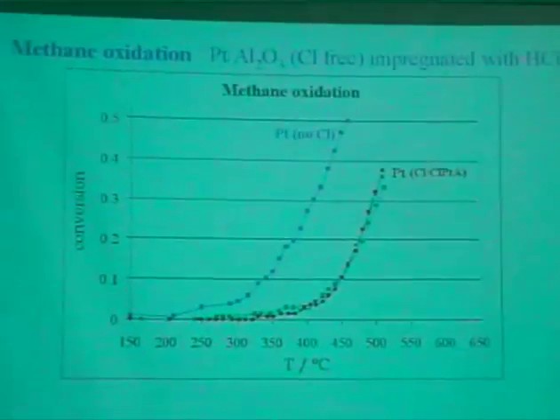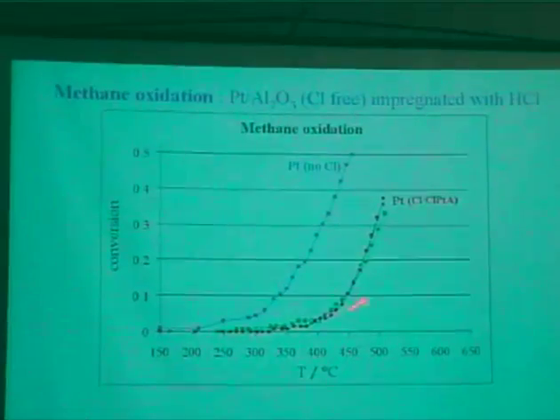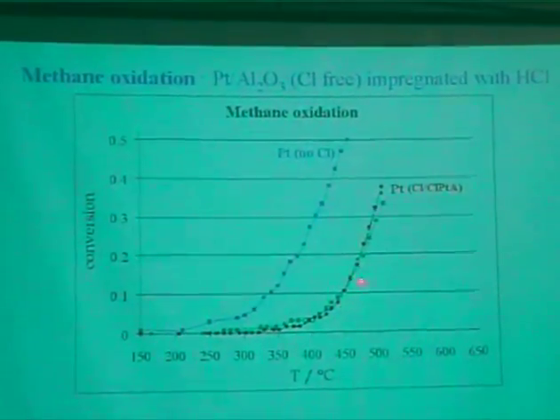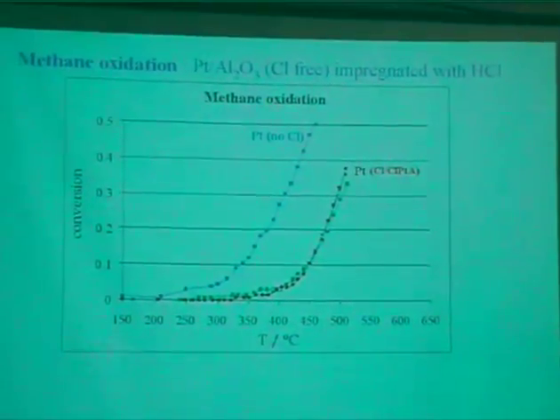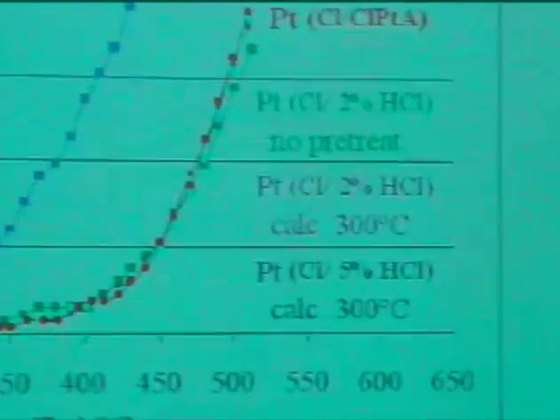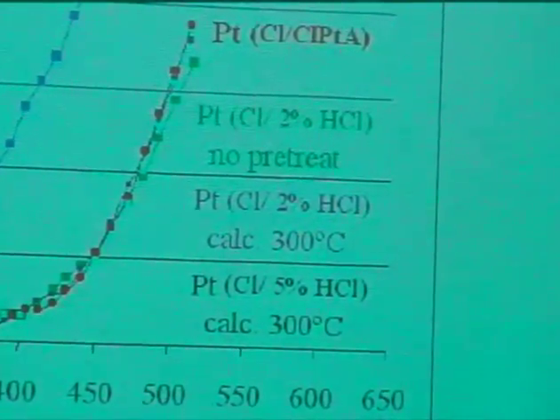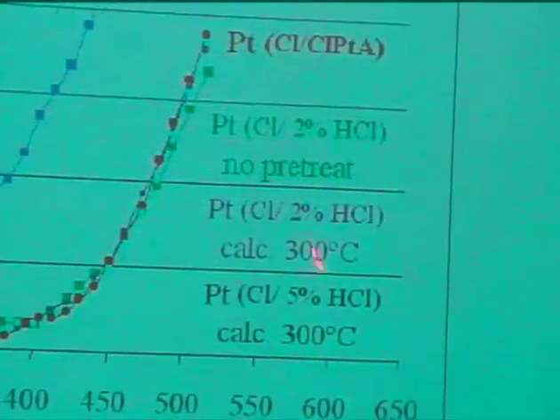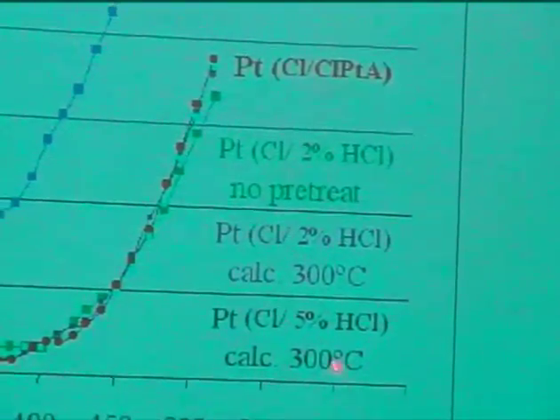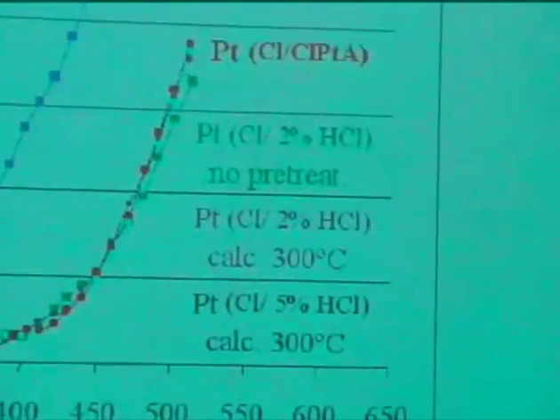Well, we thought, that's very interesting, let's try methane oxidation and see if the pretreatment makes an effect. So here we have our two base catalysts, no chlorine and chlorine-containing catalyst. And these are the other catalysts in which we added the chlorine, and there is no effect of the pretreatment. So here again, what's going on? No pretreatment is the same as when we calcine. And well, what happened here is that this reaction's temperatures are very high.